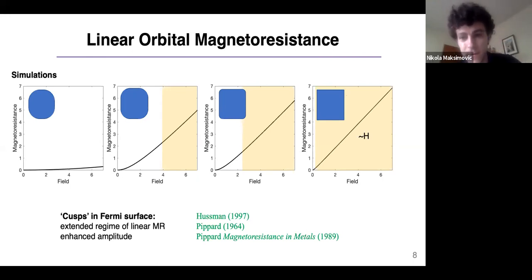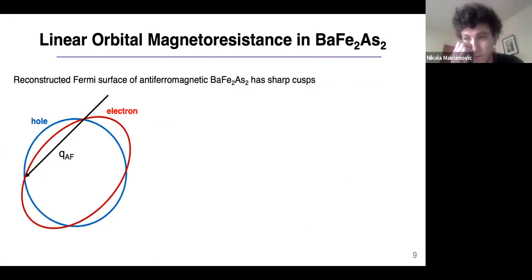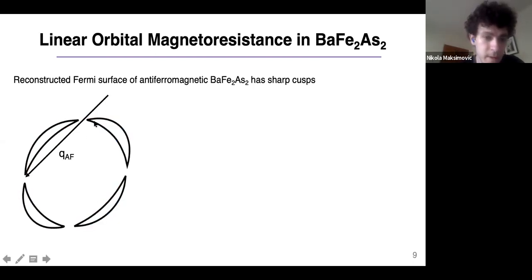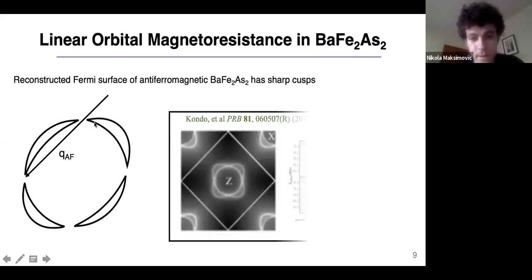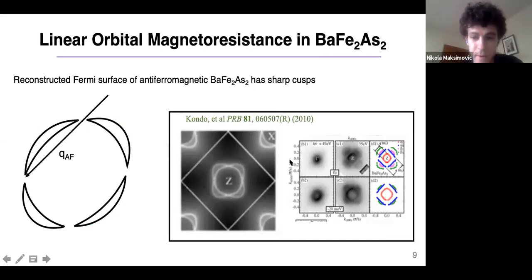So it's actually fairly rare to observe a Fermi surface that looks like this. But we have good reason to believe that the Fermi surface of antiferromagnetic barium-122 may have these sharp cusps. Here I'll show a cartoon. So you have a hole Fermi surface at the center of the Brillouin zone, electron Fermi surfaces at the corner, and they get imperfectly nested by the antiferromagnetic ordering vector. And when a gap opens up, you get these banana-shaped pockets with these regions of large curvature at the corners. To some extent, this has been observed in ARPES experiments on barium-122. These are actually simulations of the Fermi surface, and experimental data can somewhat see these banana-shaped pockets.